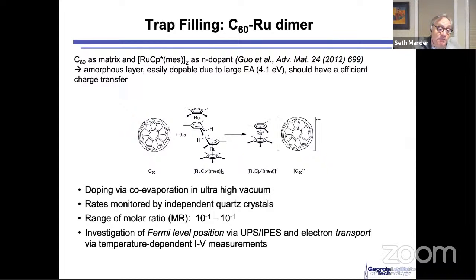and a ruthenium dimer that we had made, and to dope that. That was done under ultra high vacuum. Antoine had the system equipped with a quartz balance system where he was able to control the molar ratio from 10 to the minus 4 to 10 to the minus 1, so from 10 to the minus 2 mole percent to 10%. As I said, he examined the energy levels using UPS and IPES, and then there were transport measurements done.